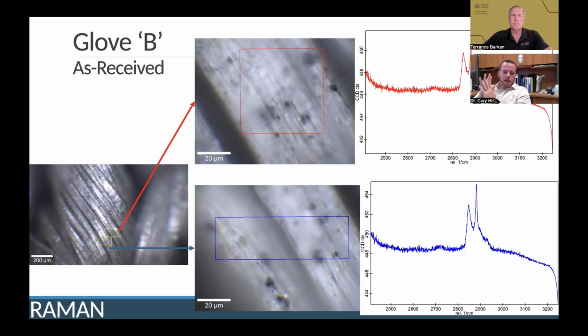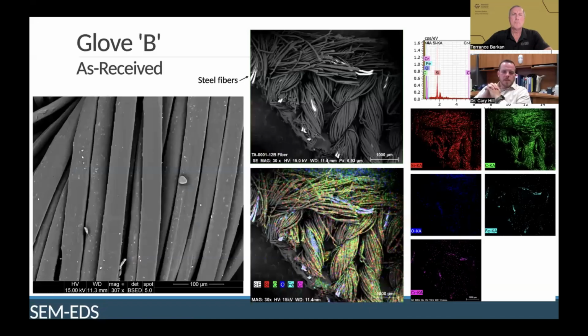So in the next slide, we have our SEM imaging of this fiber, these gloves. This is the as received glove before any extraction is conducted. And some of the interesting nuances here, this is elemental analysis. We're not going to be able to discern graphene in this particular characterization technique, but what we do see is elemental differences, which tells us things like those in that kind of top middle image is a backscatter image on the SEM, and you can see those kind of glowing fibers that are coming out, the bright white fibers. This is in backscatter mode where we see higher Z number, higher atomic number materials are going to show up brighter. And so that tells us that's a different material.